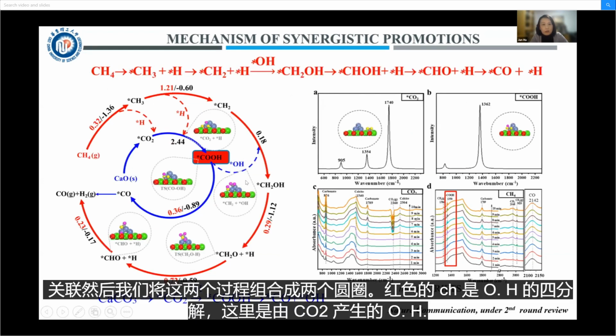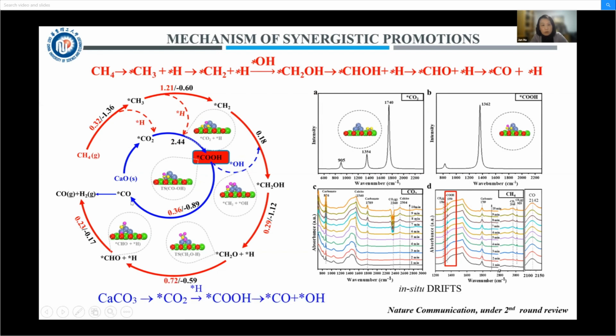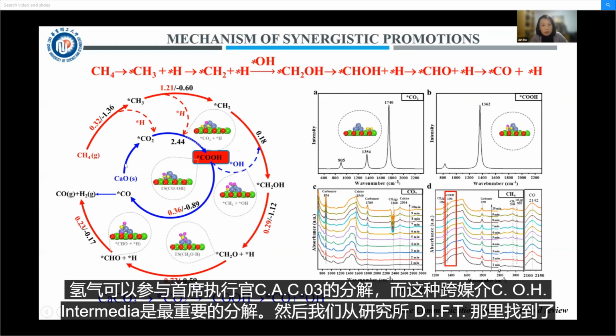We combine these two processes in one cycle, in two cycles. The red one is CH4 decomposition with the OH produced from the CO2 dissociation. Meanwhile, the hydrogen can participate in the CaCO3 decomposition, and this COH intermediate is the most important one.